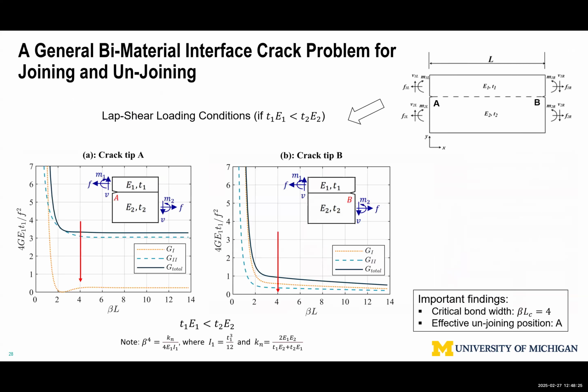And lastly, just one quick example. Multi-material manufacturing is even more challenging, right? We have a lot of trouble with same material welding, but it actually offers new opportunities. So here's the example. We can consider generically using fracture mechanics concepts between material 1 and material 2. It really doesn't matter if it's metal to metal, metal to plastic, or plastic to plastic. We identified that if you can manage to put a bond together nicely, as I illustrated here, then we can easily debond and rebond them, because now I have a clearly defined interface to work with.